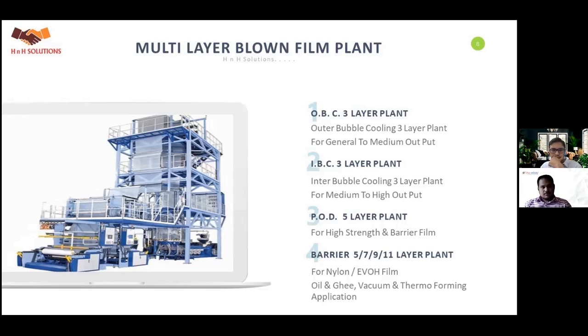It also gives high hot pack strength, so we can pack bulk product like 5 kg, 10 kg, 15 kg from this film. Barrier layer plants like 5-layer, 7-layer, 9-layer, 11-layer are available to produce nylon or EVOH film for oil, ghee, vacuum, thermoforming applications. It gives high barrier against gas and moisture.